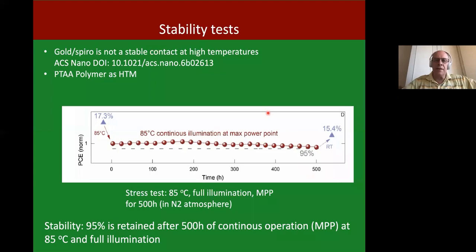Also, the stability was a very interesting result in this paper. Here we changed the spiro to a conducting polymer, PTAA, instead, which was important for stability at high temperature. And here you can see that we measure operating conditions of the photovoltaic perovskite cell for 500 hours. It's 85 degrees, continuous illumination, and operating at maximum power point. We are not sealing the cell, it's a nitrogen atmosphere to avoid encapsulation as a parameter for the stability.